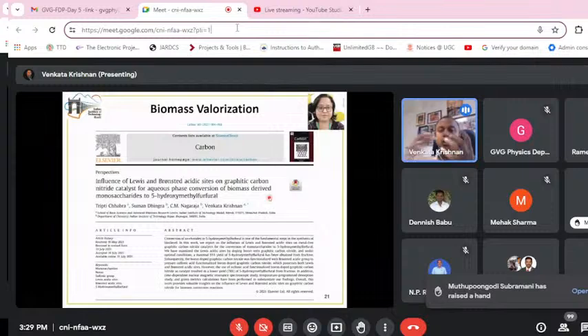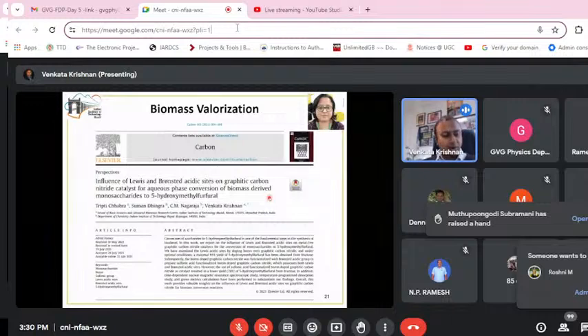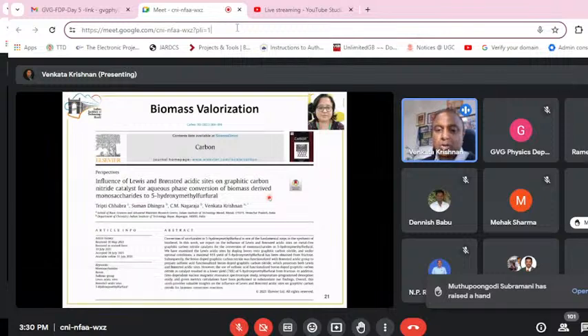In yet another work, we have done a similar type of thing, but here we have used a combination of Lewis and Bronsted acid sites on the graphitic carbon nitride. This graphitic carbon nitride was initially doped with boron, which gives the Lewis acid site, while the existing nitrogen atoms give the Bronsted and Lewis basic sites to the graphitic carbon nitride. On the other hand, when the same material is functionalized with SO3H groups, the sulfonyl groups, that imparts the Bronsted acid site to the catalyst. So the same catalyst has Lewis acid sites, Bronsted acid sites, and also different basic sites. This was used for the conversion of monosaccharides to 5-HMF, and we got some good results.